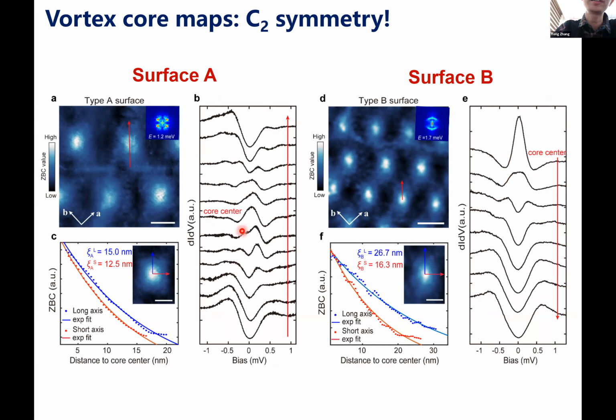And in the vortex core, we can see the vortex state. On surface B, the core shape is even more anisotropic. But at the core center, you still see the peak close to the zero bias, right? But now it's not a zero bias peak. Actually there are many peaks. We see an envelope of these peaks. And we can take a line cut along different directions of the vortex. And you see the coherence length can be fit from this line cut. And they are different along the two particular directions.